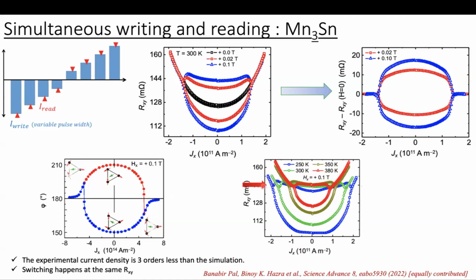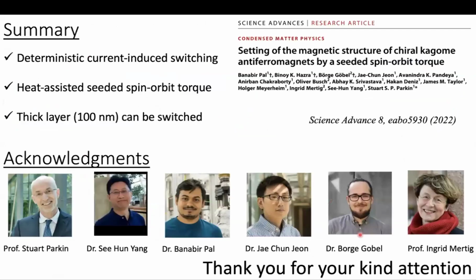This particular Rxy basically tells us that the system heats up to a certain temperature, which corresponds to this fixed Rxy value, and then switching happens. Whether it's 250 or 380 doesn't matter. The system reaches, let's say, 450, and then it cools. So this fixed Rxy basically tells us the switching is again heat assisted. So in summary, we observe a deterministic current induced switching, and heat plays a crucial role.